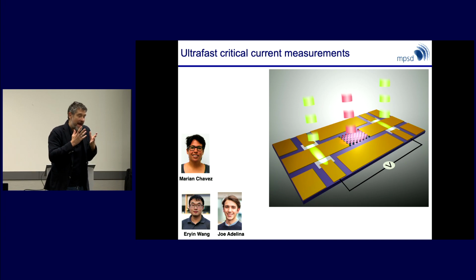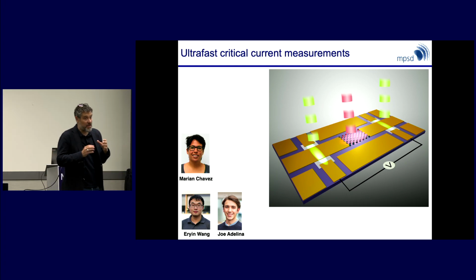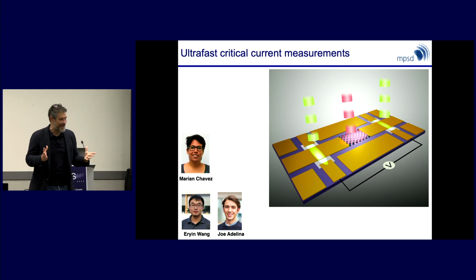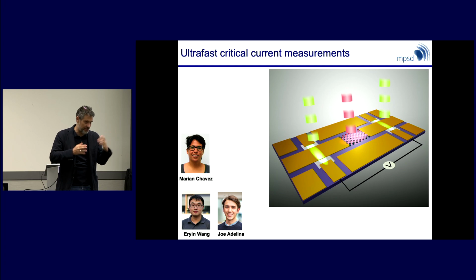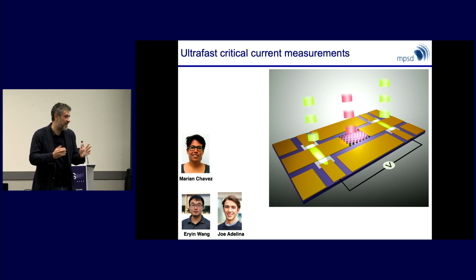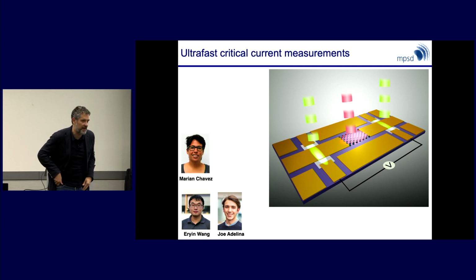The films are thin, so there are no penetration depth problems, but in a wide field measurement, you can't really convince yourself that you can back out the microscopic parameters. You're talking about the kinetic inductance here, so basically the scattering rate. Basically, the density. Not really. I mean, as I said, you can forward fit, but if you have enough parameters, you can forward fit anything.